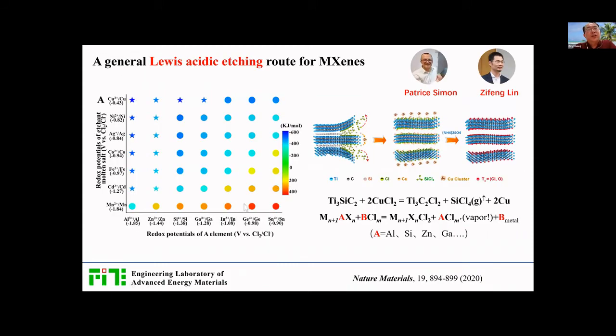Here we can generalize this molten salt approach to make MXenes, because we know there are many MAX phase family members. In these mapping images, you will see that if we choose the proper Lewis acid melt, we can etch almost all MAX phases, whatever the A element. So I think it's a guidance for choosing the suitable Lewis acid melt.